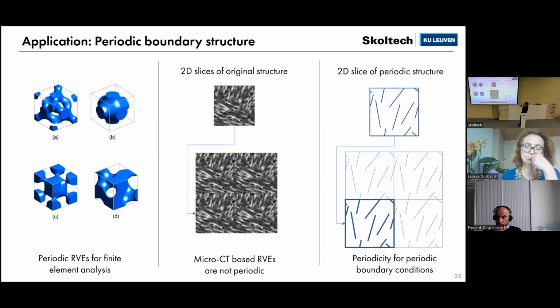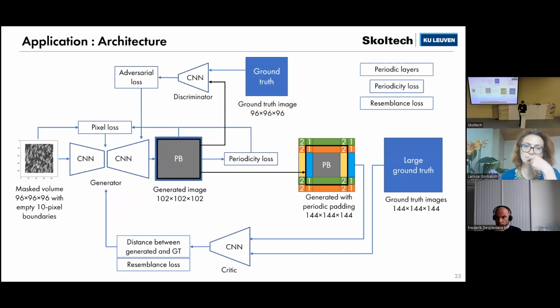This is my example. So we have, for example, a fiber here in a periodic way. It goes from one border to another border to be periodic. And for this, I also used an inpainting algorithm, but with some modifications. It also consists of a generator, a discriminator, and an additional neural network. This is the critic. Basically, the critic analyzes not only the generated part, but the image overall as periodic. So it also analyzes it with periodic padding. And also we have modifications such as periodic layers, periodicity loss, and resemblance loss. So basically the idea of all these losses is quite similar.